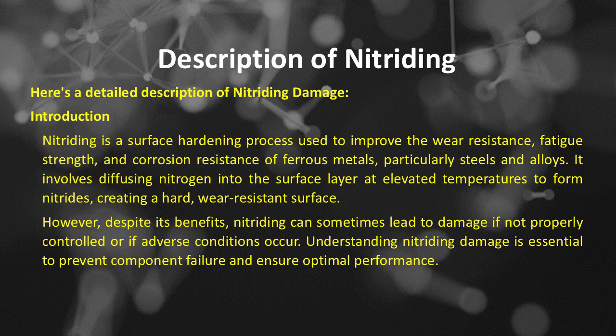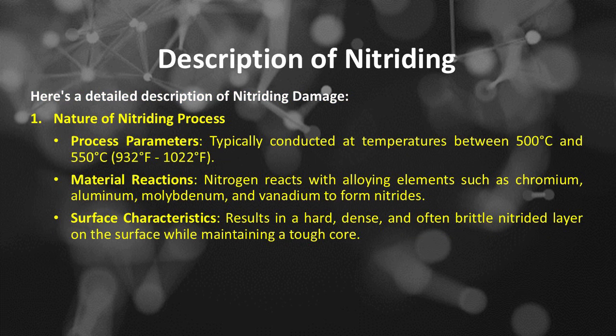Introduction: Nitriding is a surface hardening process used to improve the wear resistance, fatigue strength, and corrosion resistance of ferrous metals, particularly steels and alloys. It involves diffusing nitrogen into the surface layer at elevated temperatures to form nitrides, creating a hard, wear-resistant surface. However, despite its benefits, nitriding can sometimes lead to damage if not properly controlled or if adverse conditions occur. Understanding nitriding damage is essential to prevent component failure and ensure optimal performance. Here's a detailed description of nitriding damage.